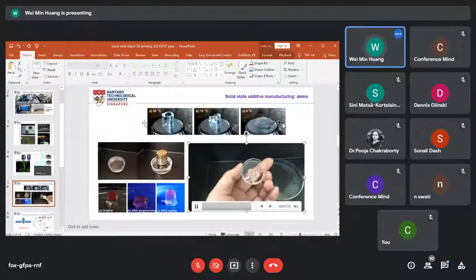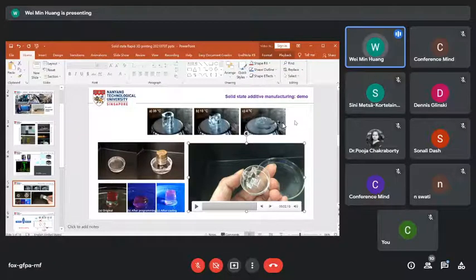We successfully produce this cross shape by dual cross-linking in solid state. But only in the last step do we actually get rid of the uncrosslinked part. The tricky part actually is that we needed the shape memory effect to ensure that the model we printed is precise, because without it, during removal of the uncross-linked part, the crossing part may be distorted. So we need to check the shape memory effect, as shown over here.